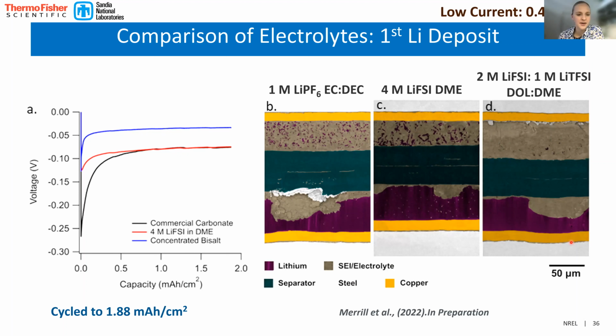And so in comparison of 1 molar LiPF6 in EC-DEC compared to 4 molar lithium FSI and DME compared to a mixture of 2 molar lithium FSI with 1 molar lithium TFSI and DOL DME, you can see that there's a variation in the cycled structure. So this is just the first deposit of lithium from the counter electrode to the working electrode. In the carbonate electrolyte, you can see that there's very small lithium deposits that formed. They're very spread out, and a lot of SEI has formed.